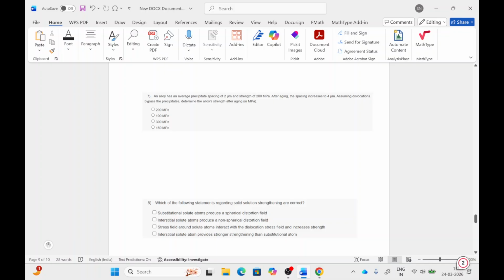Coming to the seventh question: an alloy has an average precipitate spacing of 2 micron and strength of 200 MPa. After aging, the spacing increases to 4 micron. Assuming dislocation bypasses the precipitate, determine the alloy strength after aging.